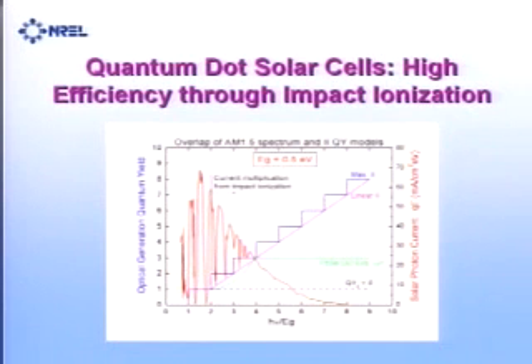As I say, we're going to ultimately try to develop this for Grätzel cells and other devices, which I'll briefly show. But you can make a calculation of the improvement in the efficiency depending on the absorption characteristics. In the best case, for each band gap, you'd have another electron hole pair generated. So you'd have a staircase here up to 7 or 8 electrons per photon at high enough energies.